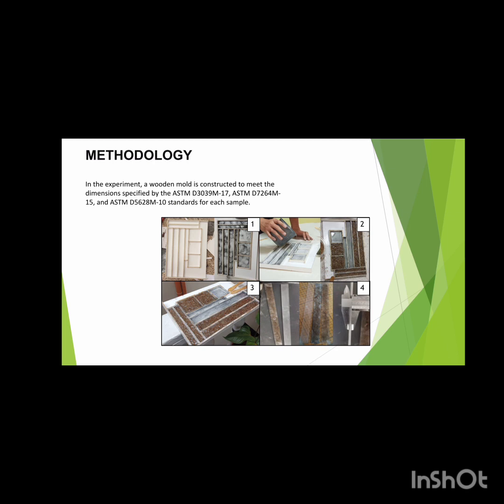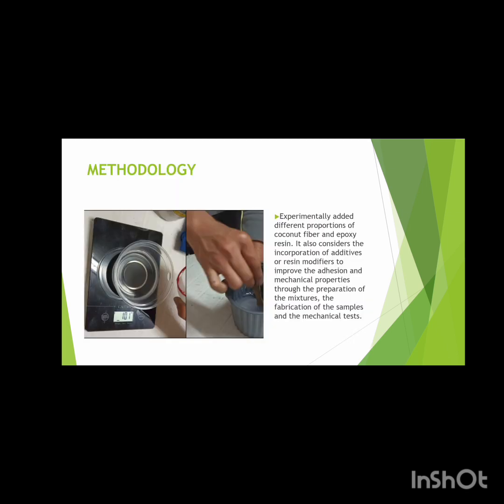Methodology. First, we have to obtain coconut fibers from the coconut. For this, we have to heat the sheet of the coconut several times, and also prepare the epoxy resin that has two components, the additive and the catalyst. Continuing with the process, a wooden mold is made with the dimensions of each sample based on ASTM standards. The correct proportion of catalyst and additive is 1:2, so we took care when mixing both components of the epoxy resin.